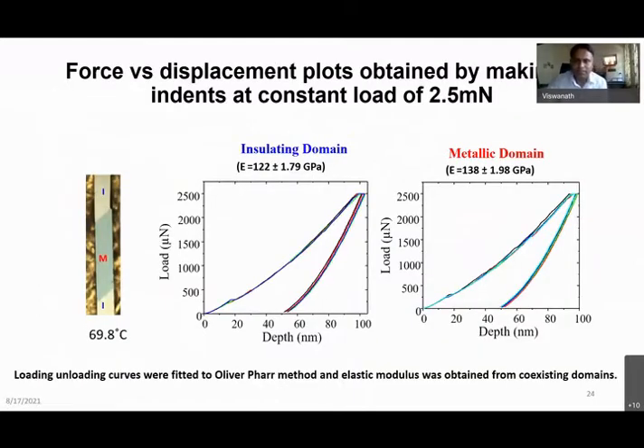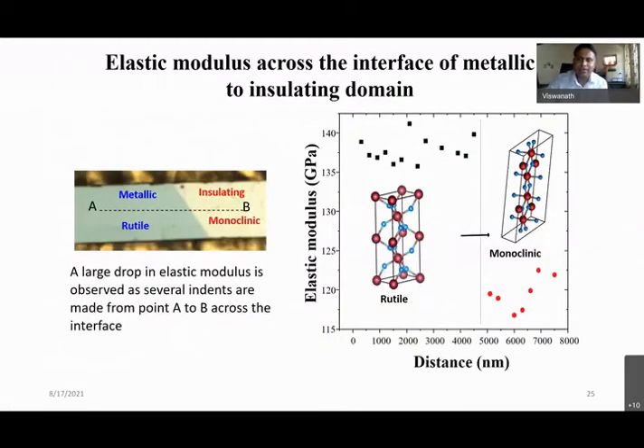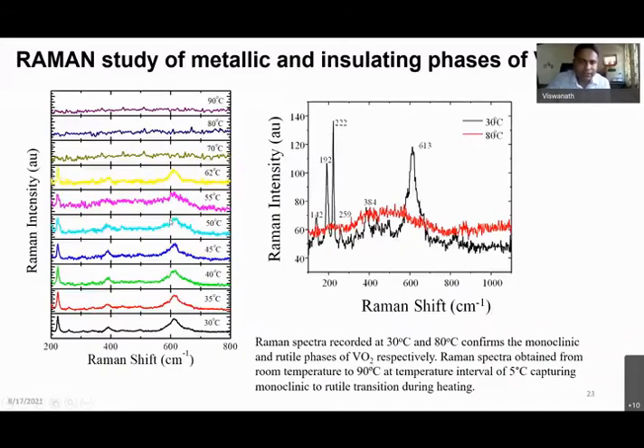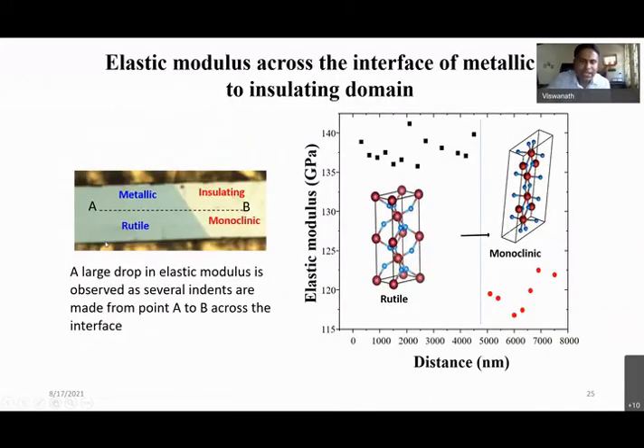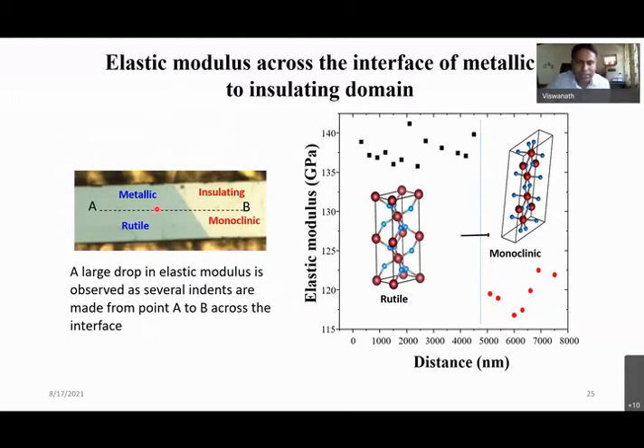After that, we try to do indentation on the insulating domain and the metallic domain. So we are able to clearly get consistent values. As I said earlier, there is a 15 to 17 gigapascal change. But in addition to measuring properties as a function of temperature, we also have coexisting phases, like exactly this particular beam, at around 69.6 or 70 degrees Celsius. We can have both metallic and insulating domains together. So it is possible to do indentation across the phase boundary from metallic to insulating. That is what is shown here.